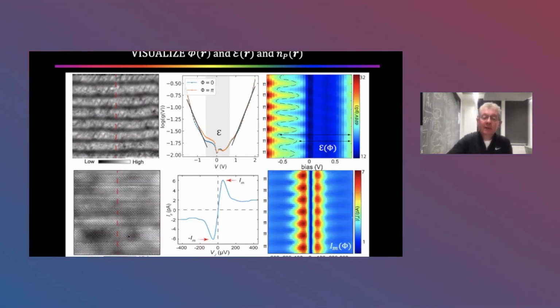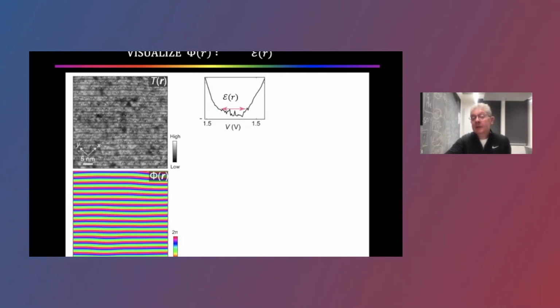And similarly, if we have a superconducting tip, we see the supermodulation of the crystal. We measure the maximum in the pair current along the red dashed line. If I plot the pair current magnitude versus energy in microvolts along that line, it's modulating. So these are facts. There's no theory involved here. I mean, you have to agree that the experiment is working, but there's no theory involved here. The energy gap between the two bands is modulating, and the Josephson current is modulating with the supermodulation.